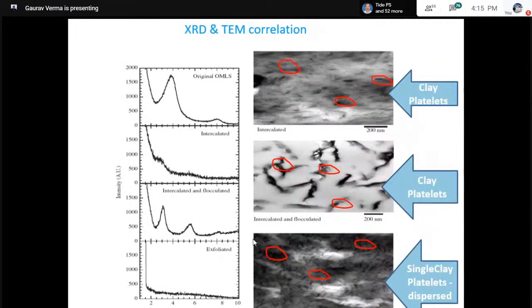So what we have to do is correlate by conducting transmission electron microscopy, wherein the sample size is very small and you are looking at a scale of around 200 to maybe 100 or less than 100 nanometers. And you see the actual clay platelets or the 2D nanomaterials which we were trying to explore for a nanocomposite.